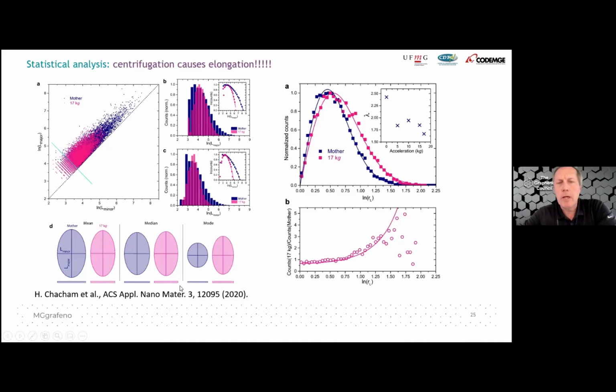So Luis, I think you guys have a real breakthrough with this technique, and I'll share some additional questions that I have. For example, with AFM, as you mentioned, you have a problem with selection bias. If you're doing individual measurements, people can pick which flakes they want to characterize. The other problem, of course, is that even with 10,000 flakes or 1,000 flakes, it's still, relatively speaking, an extremely small sample size compared to the total amount of material. But what you're doing is a step change improvement because of the number of flakes that are actually being read.